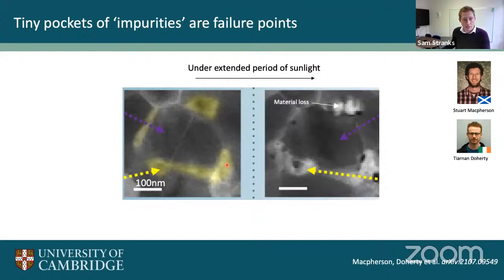And so this is some experiments where the yellow shading is these sites that are problematic, and they're slightly different structures to the perovskite. When we look at them in an electron microscope before and after lots of light, you can see lots of changes to the material at these sites. In fact, we have material being lost here, and eventually they form little pinholes, so you actually lose the material entirely. And this is, of course, not good for long-term operation of a solar cell. We need to get rid of these. So this is telling us a lot of information about how we can understand these cells, and then how we can improve things.